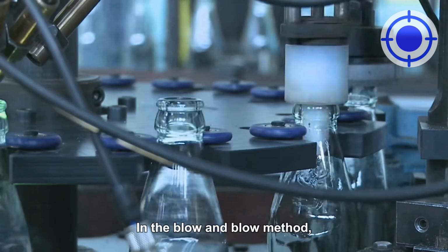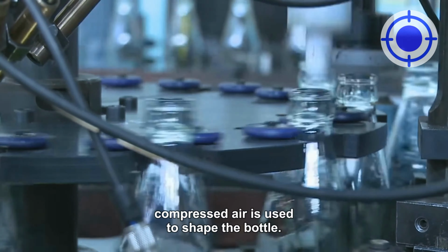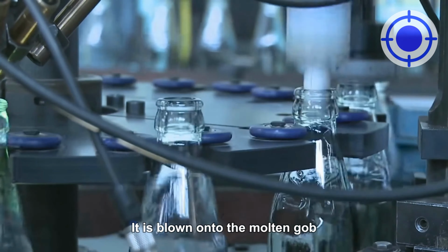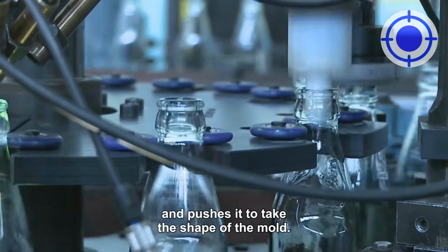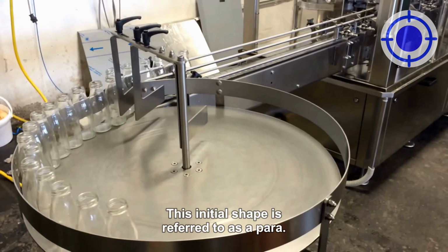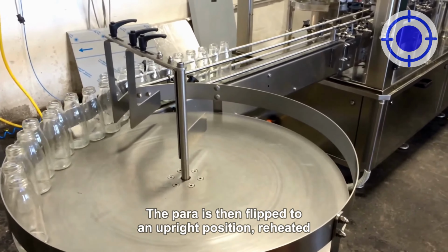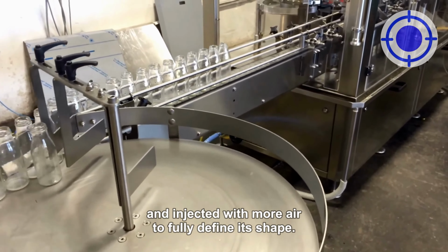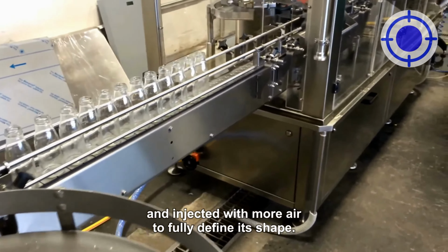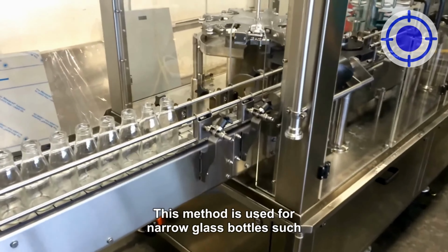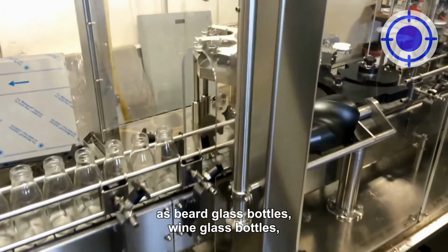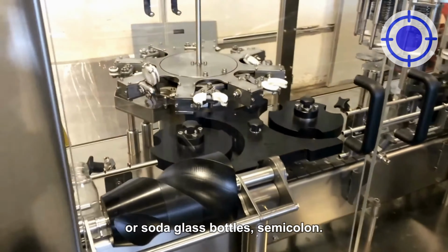In the blow and blow method, compressed air is used to shape the bottle. It is blown onto the molten gob and pushes it to take the shape of the mold. This initial shape is referred to as a parison. The parison is then flipped to an upright position, reheated and injected with more air to fully define its shape. This method is used for narrow glass bottles such as beer glass bottles, wine glass bottles or soda glass bottles.